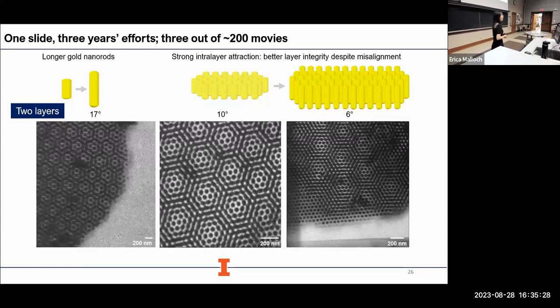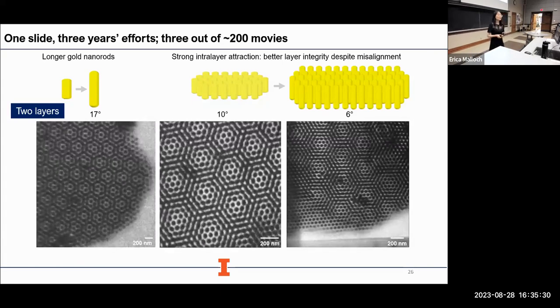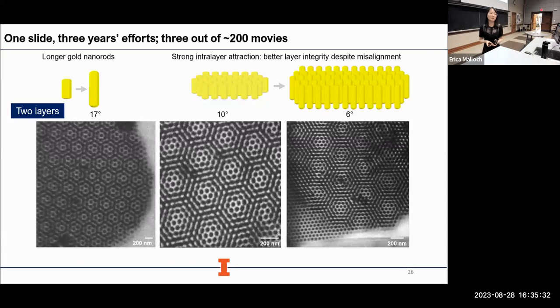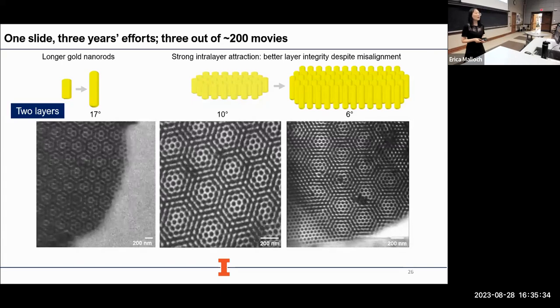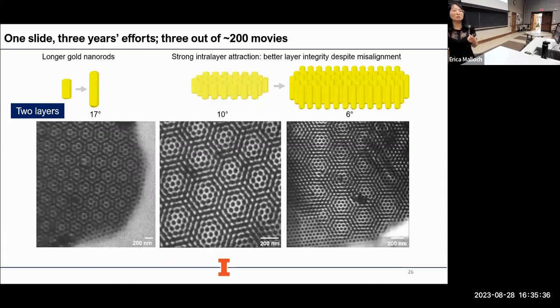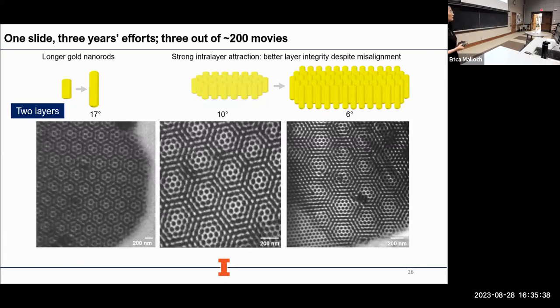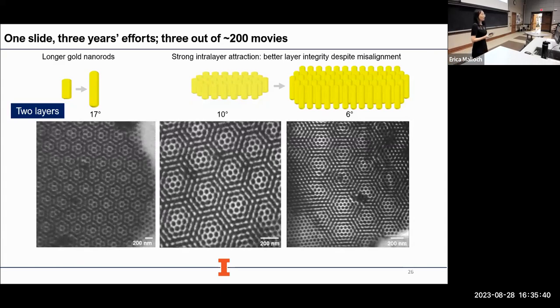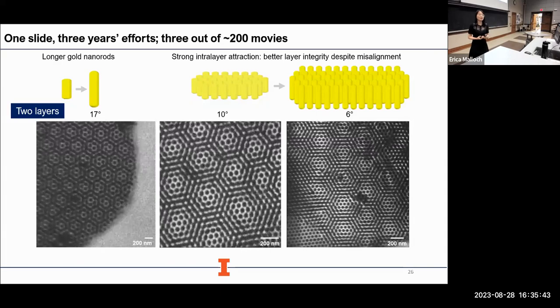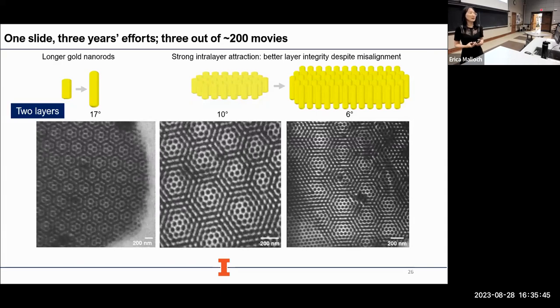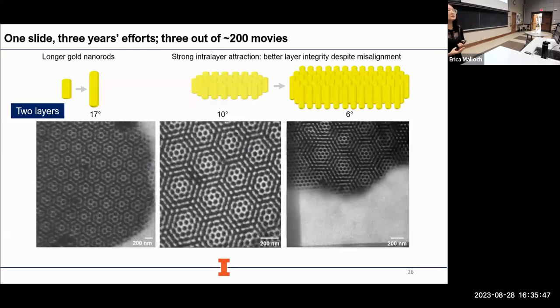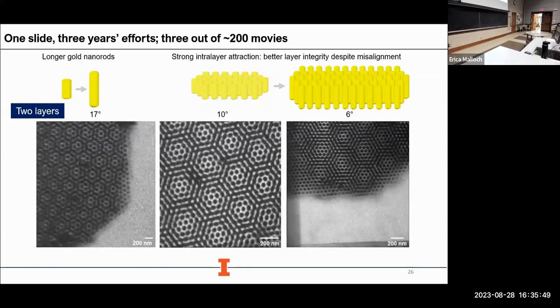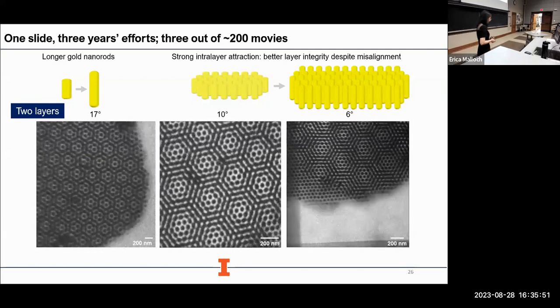So I'm showing on this one single slide, 3 years effort. I'm showing 3 movies out of more than 200 movies. And that is because it turns out this is a really robust system to generate moire patterns. It's also because we have a huge library of gold nanoparticle building blocks out there. So we have a large tunability in terms of moire angle and the intralayer coupling.